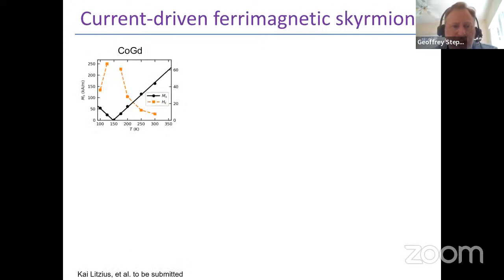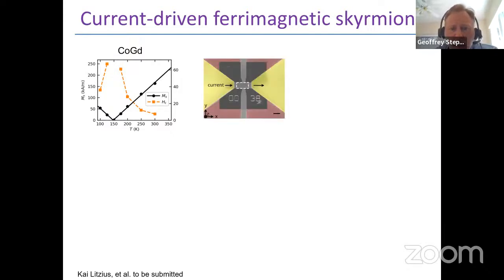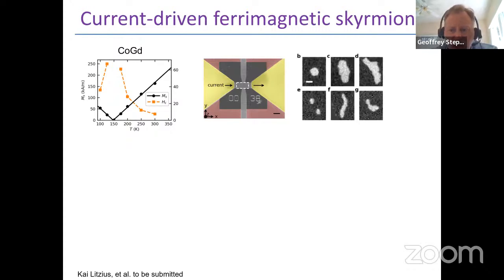When we look at these kinds of materials, not just at domain walls, but magnetic skyrmions, we have looked at cobalt gadolinium, both near and away from compensation. We've looked at stray field stabilized skyrmions, and we've looked at skyrmions near the magnetic compensation temperature, in which stray fields play a much smaller role. Magnetic skyrmions in these materials can be relatively circular, or they can be very large. And so the structure, the geometry of skyrmions can vary significantly.